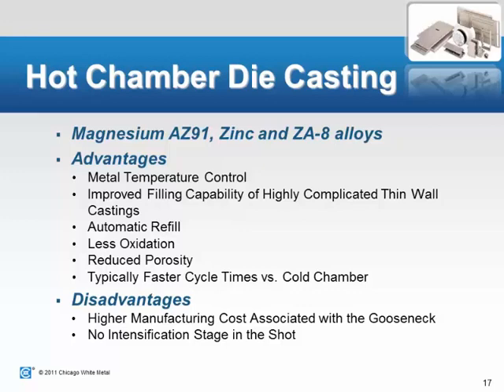Some of the advantages: we're able to control the metal temperature better, improve filling capability of the thin wall castings, and reduce porosity because of the way that it enters the tool and is able to fill the thin wall. We're able to control porosity better. And as I mentioned before, it's typically a faster cycle time than the cold chamber, which helps with the process costs.